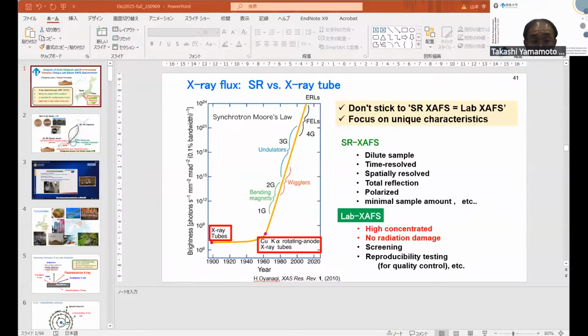I think the major advantage of the laboratory is that the intensity of the X-rays is very weak. It means radiation damage is very low. Sometimes high flux synchrotron radiation X-rays destroy samples, such as hydroxides, or reduce samples or cells. But laboratory-type X-ray sources are very weak, so the risk is quite low.